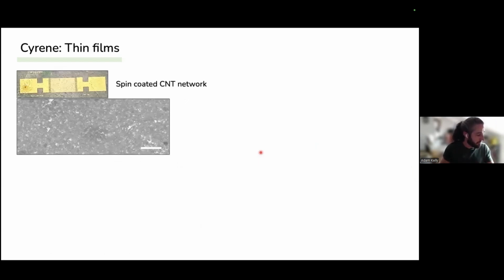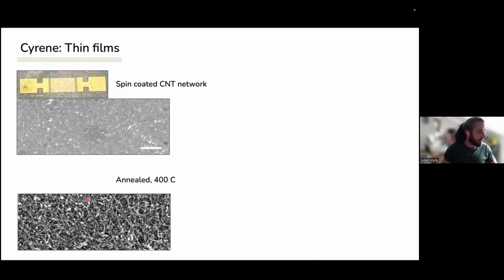And if you're going to be spin coating, you need larger masses of material. So we had plenty of carbon nanotubes on hand. And we spin coated a carbon nanotube network onto these electrodes here. So this is a carbon nanotube network as spin coated. Then following annealing, we were able to remove most of this solvent. But again, because of this condensate in here, this is what the electrode and thin film looked like afterwards, which was pretty nasty.